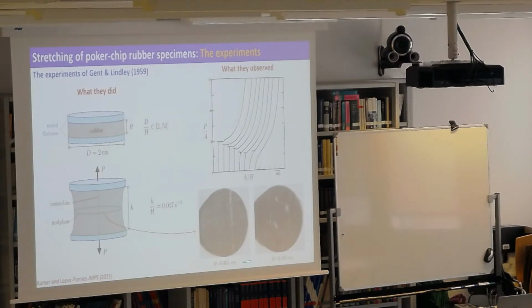Here you have a picture of the thinnest specimen, very thin. You have many, many cracks that look more or less like discs. If you go to a somewhat thicker specimen, you do not have many cracks. You only have a few, but the geometry is very different. So this is the midplane, right? So you're looking at the specimen in the midplane from the top.